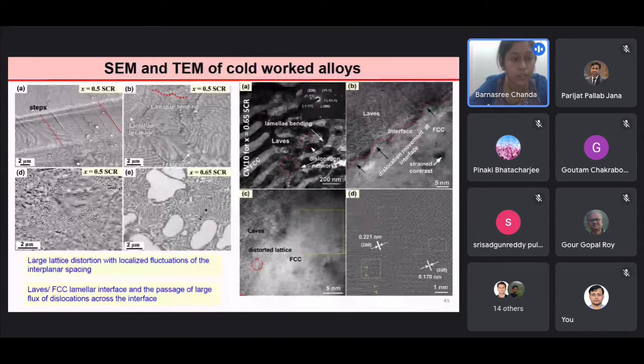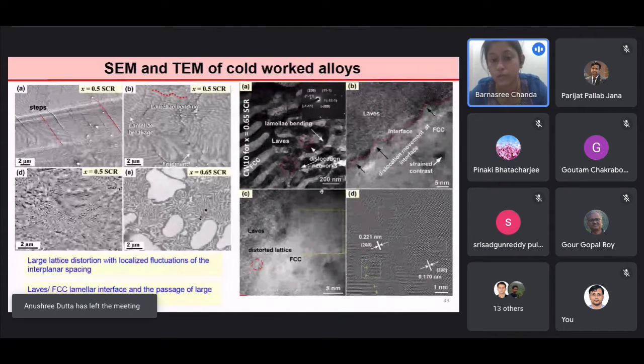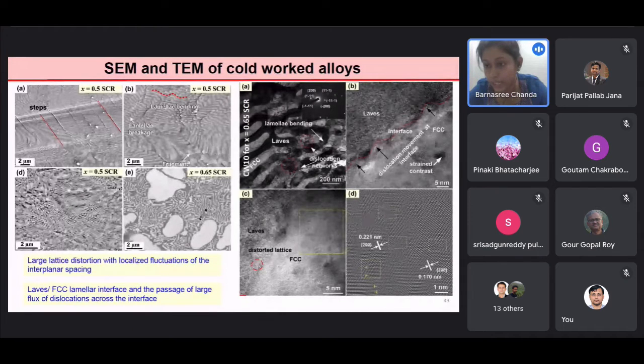Scanning electron microscopy of the deformed sample shows the presence of steps, lamellar bending and lamellar breakage. The transmission electron microscopy image for the 10% deformed sample shows the presence of a dislocation network and dislocation movement activity in the interface. Therefore, we can see that the deformation mechanism is the dislocation interaction and the dislocation in the interface. Also, in the FCC phase, we can see that large lattice distortion with localized fluctuation of the interplanar spacing can be observed.